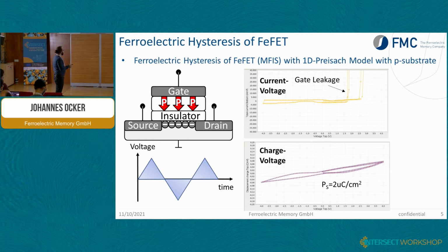And so basically you can sweep up here and sweep down, and during the down sweep on this flank, it already starts to depolarize again. And this comes from this depolarization field. So once you put in some dielectric layer, it's very difficult to really stabilize the full polarization.